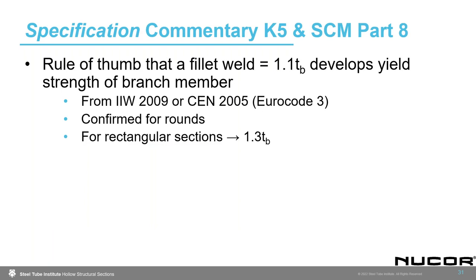There is a rule of thumb that in the past I've been asked about that I wanted to bring up here and provide some clarification to. There was a rule of thumb that a fillet weld that's equal to 1.1 times the thickness of the branch will develop the yield strength of the branch member. You can find that in the specification commentary in K5. You can also see it referred to in the Steel Construction Manual in Part 8. That originates from some work done and published in IIW in 2009 and also in Eurocode 3. Recently, this has been confirmed for rounds, so it still can be a rule of thumb that you may use for rounds.